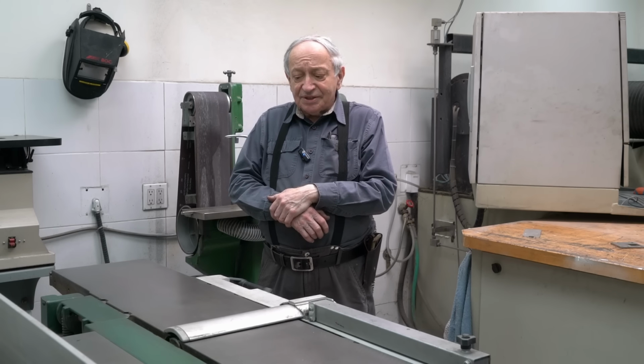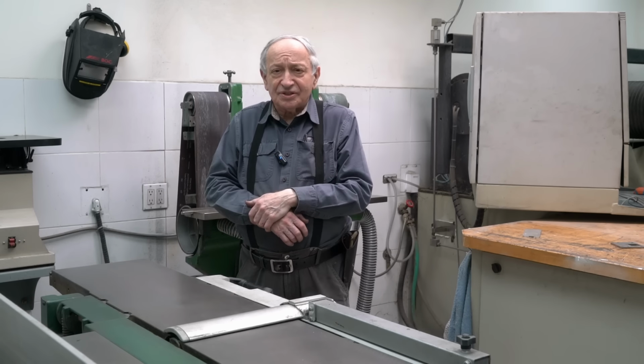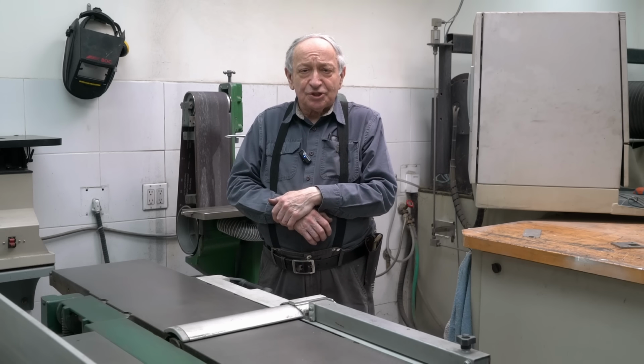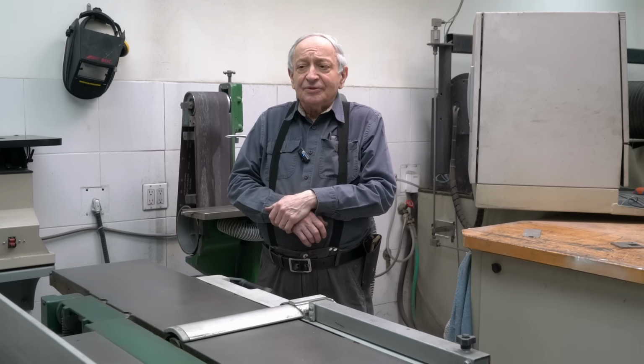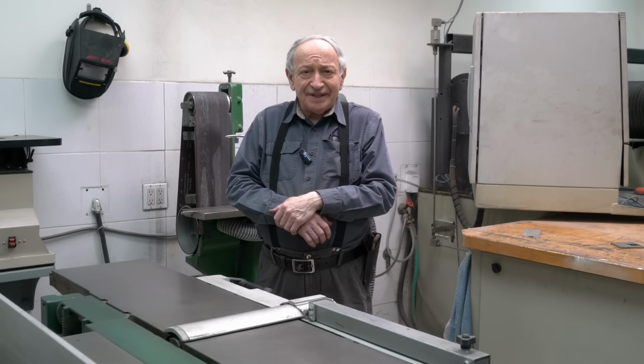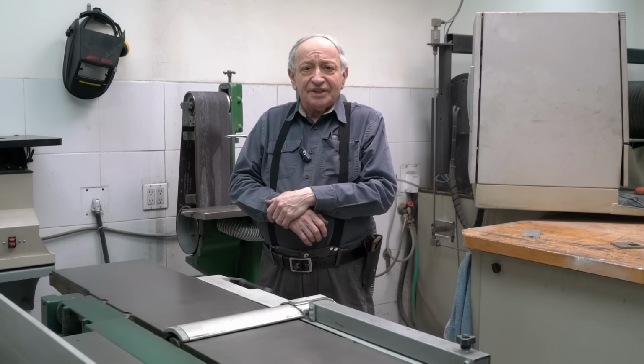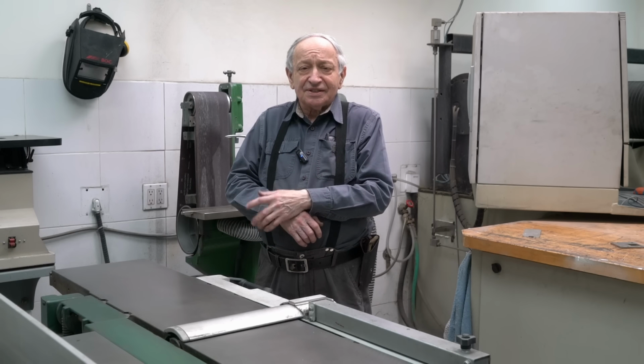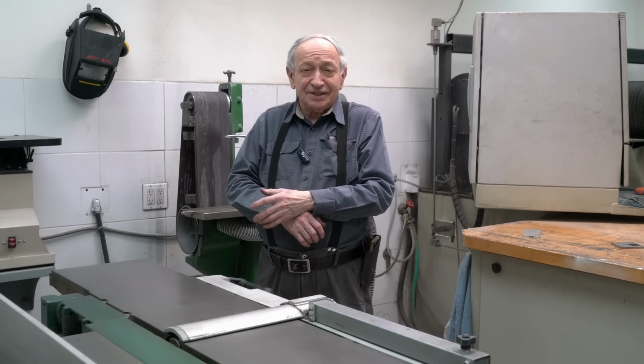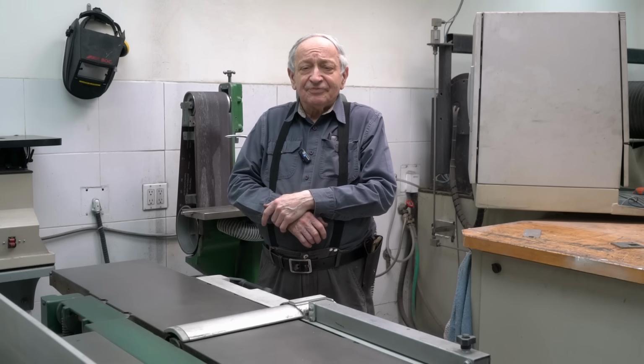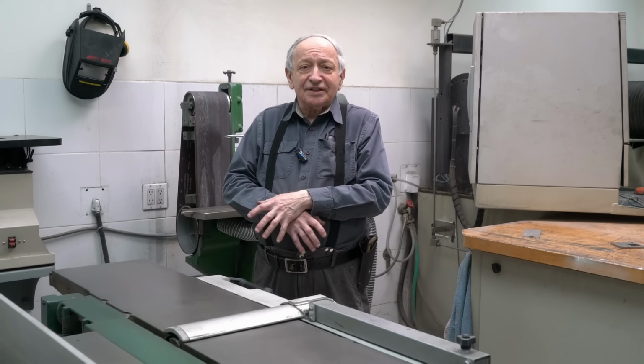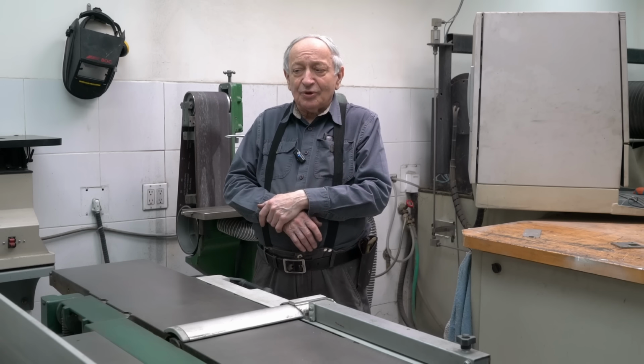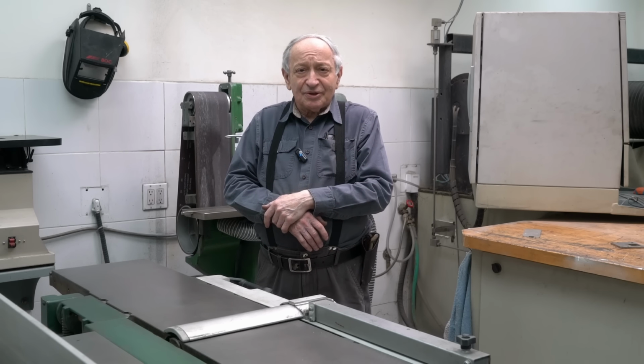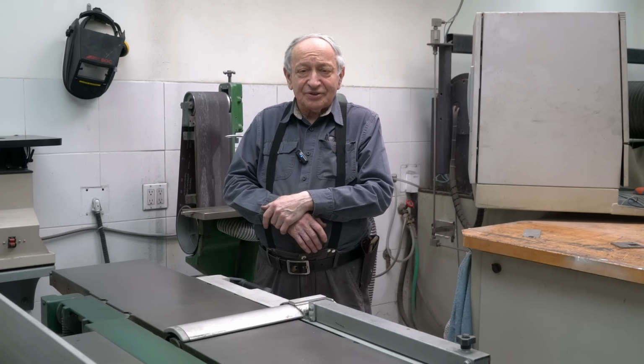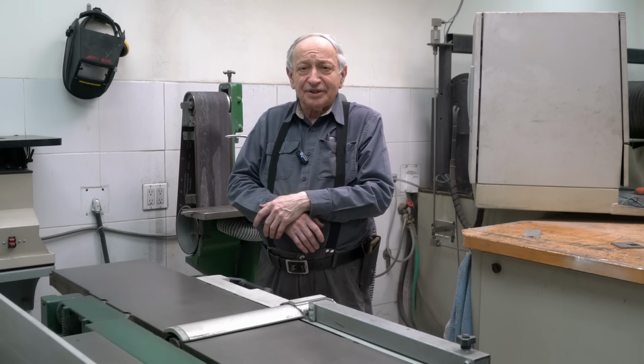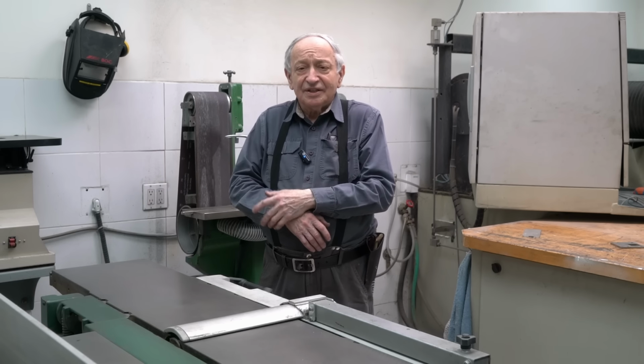The best example for that is those steel wool pads used in kitchens to scrub dishes, and you can see the steel wool pad is covered with some soap, and it can sit there for days and it doesn't rust, although it's always wet and it's steel wool, which is a lot of surface area, and one day the whole pad suddenly rusts. And this happens when all the soap is washed out, because the soap makes it alkaline. So as long as there is alkaline environment, meaning pH above 7, there is no rust.